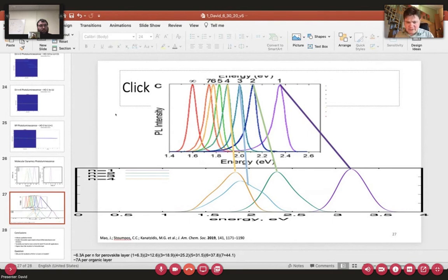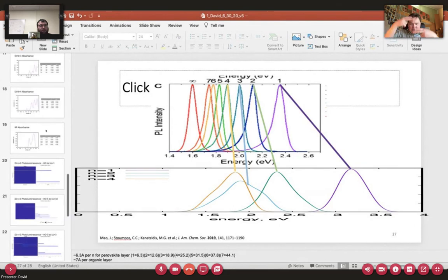If the lowest transition happens from HOMO and HOMO minus 1 to LUMO and LUMO plus 1, and if the lowest transition is fourfold degenerate, maybe it could be reasonable to include the 4 lowest transitions in the MDPL calculation. I'm just throwing in an idea.